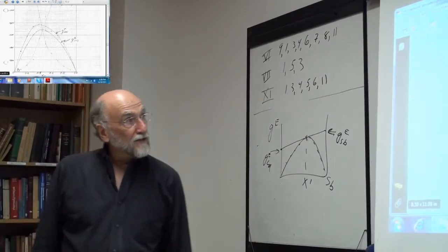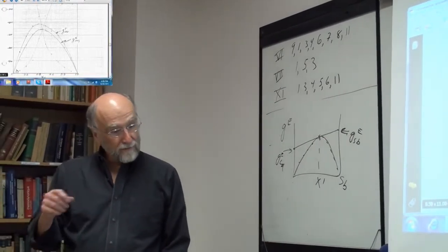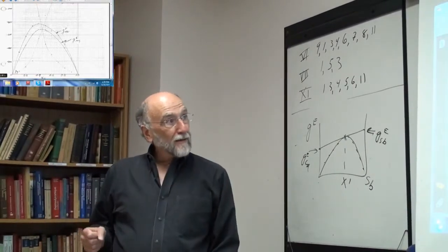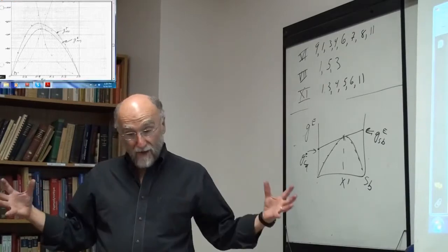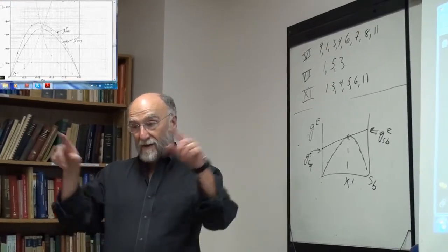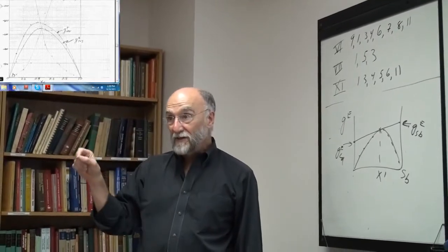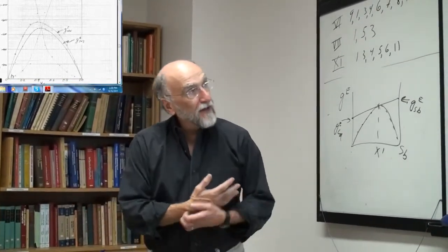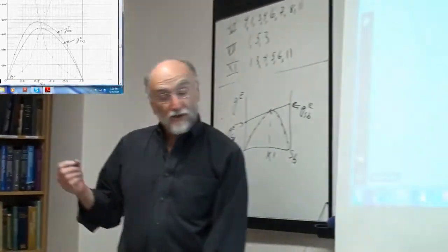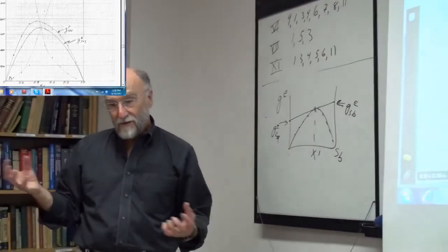But what does that mean physically? The log x is based on the distribution, the number of ways. If you have an extremely large amount of a material, the number of ways of adding one atom of zinc is equal to infinity. But the excess Gibbs property is due to the fact that you don't actually have an ideal solution. It's due to the difference in bond energy.